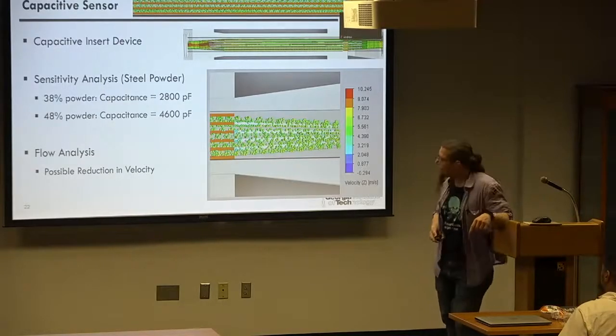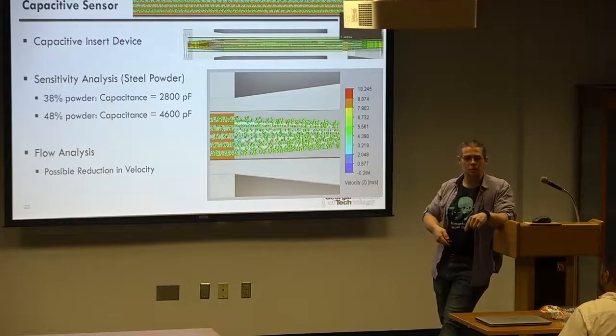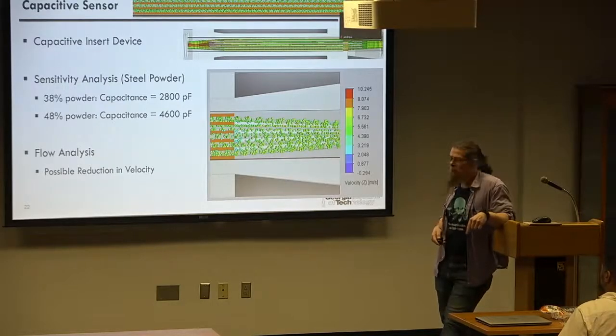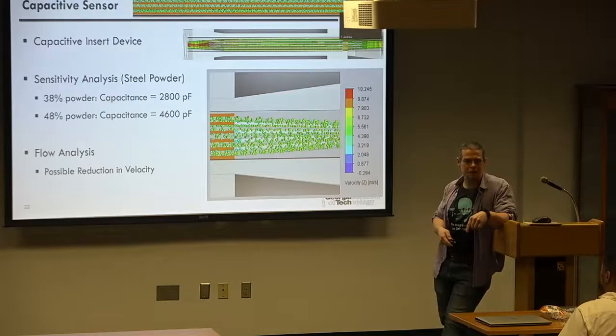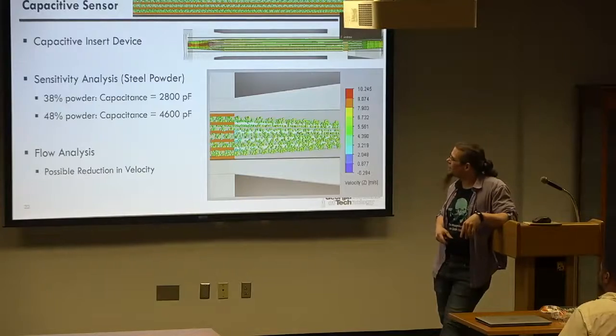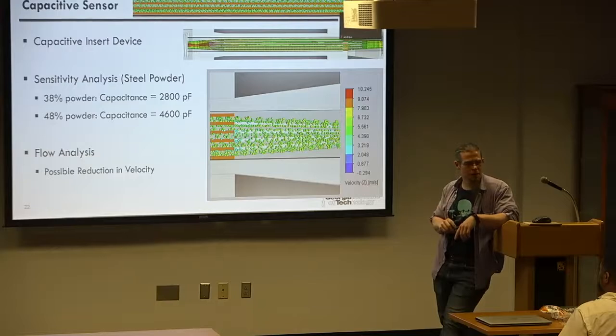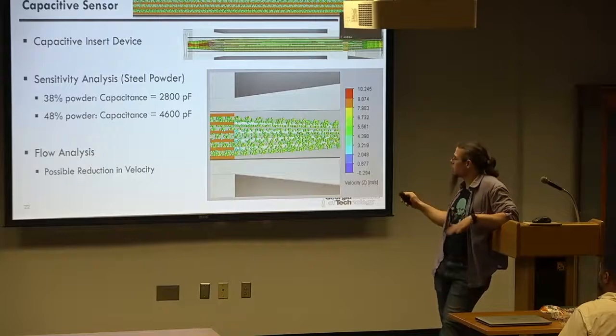Nope, it was fine. Except for a tiny little pinhole leak somewhere in the system. And we didn't find it for a couple weeks. And then we had a little pile of powder underneath the device. By the time we actually found it, we cleaned that up. We tore it apart to try and find out where that little flaw was. We're making the second prototype now, hoping in a couple weeks to plug it up and actually start collecting data. Right, so that's sort of where we are on the capacitive sensor.